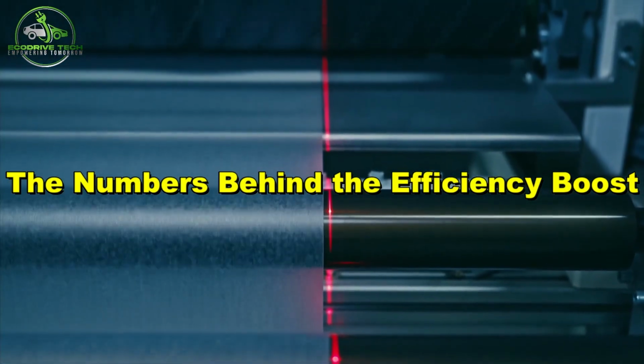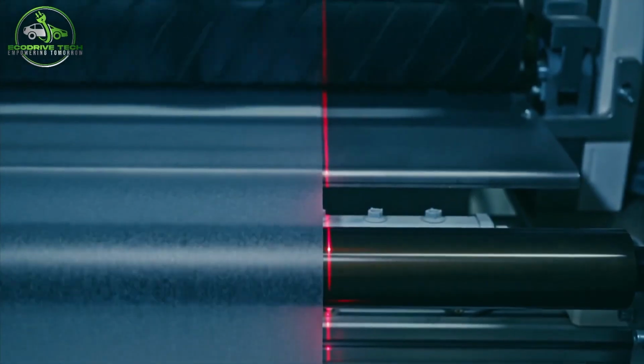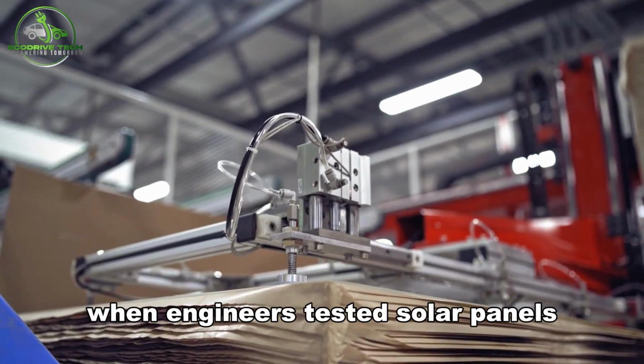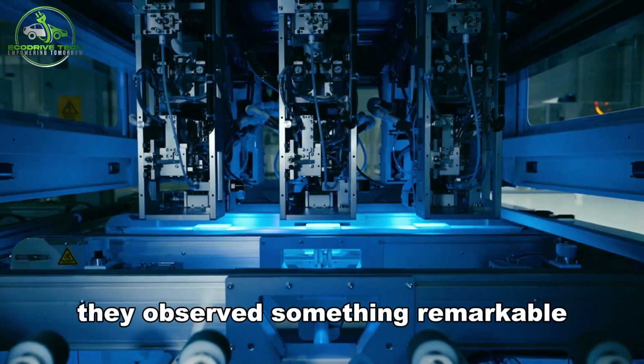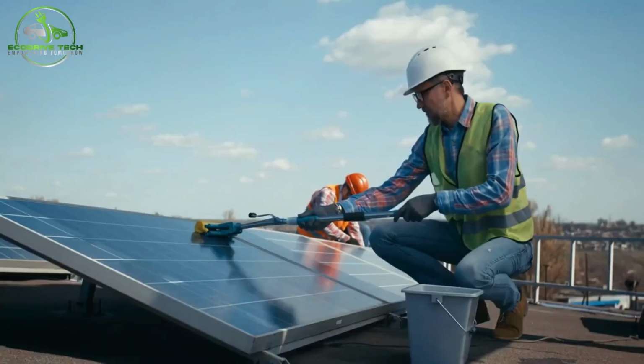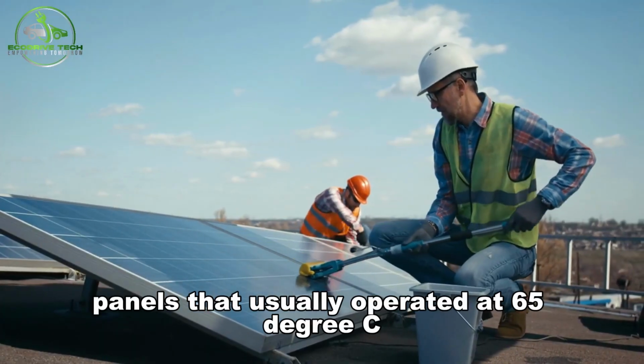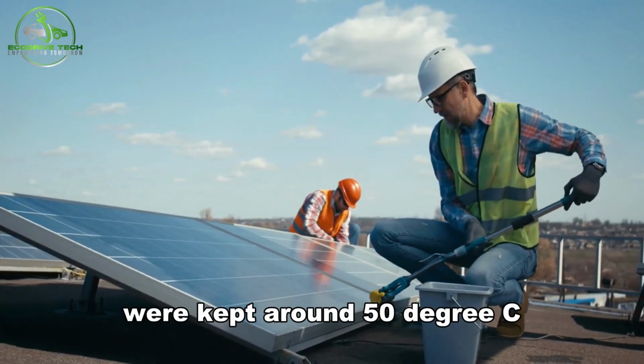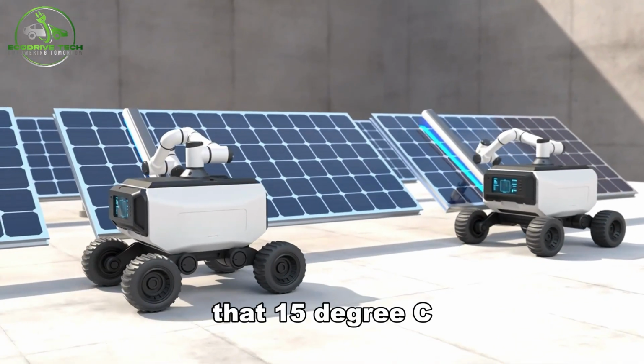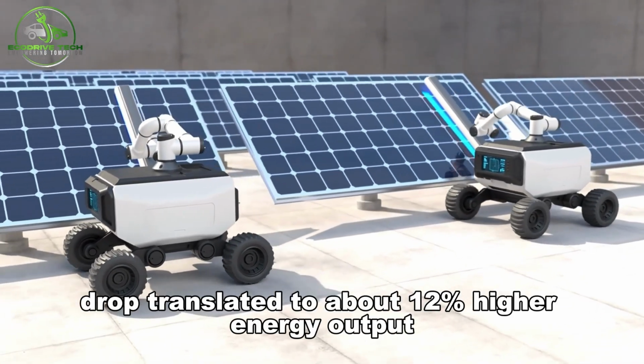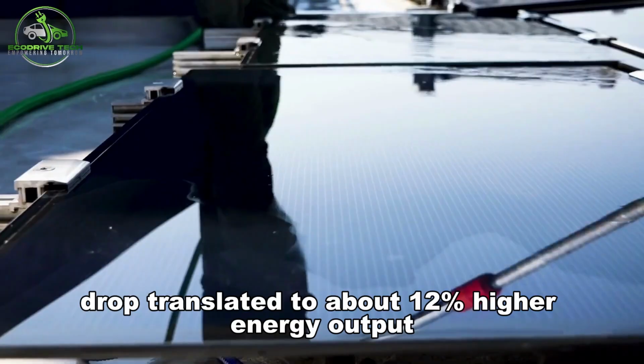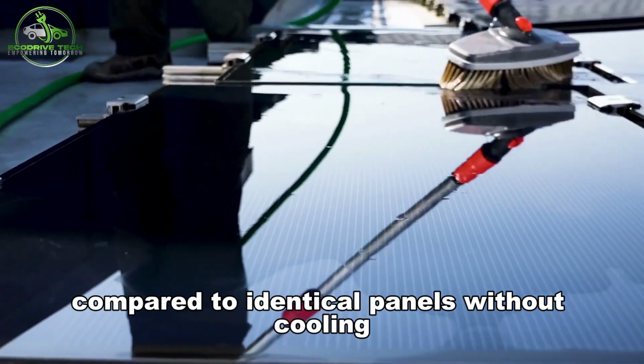The numbers behind the efficiency boost. When engineers tested solar panels equipped with the hydrogel, they observed something remarkable. Panels that usually operated at 65 degrees C were kept around 50 degrees C. That 15 degrees C drop translated to about 12% higher energy output compared to identical panels without cooling.